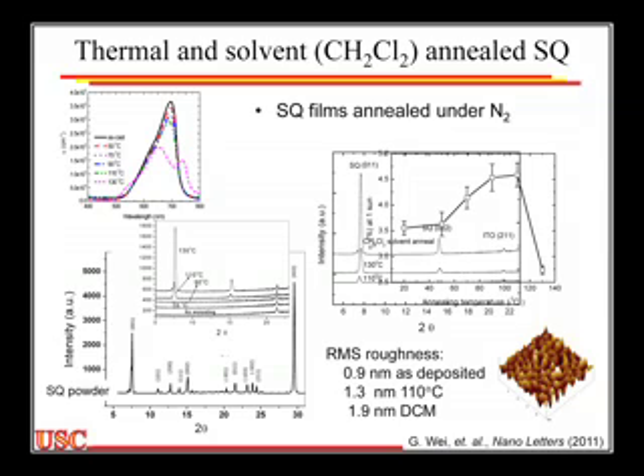If we go to 130, it gets even bigger. It's a little bit clearer here. If we anneal with methylene chloride, it gets huge. And so the question is, we're getting crystallinity built into these films. I'll show you what the structure of this is in just a few minutes. But the question is, does that crystallinity help? It should, but does it help?